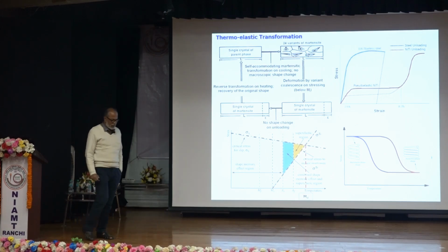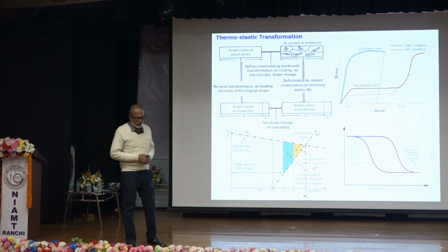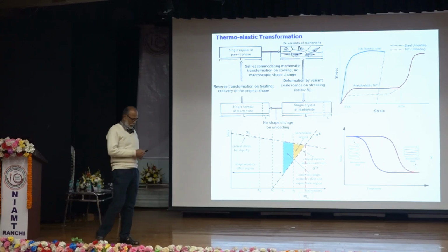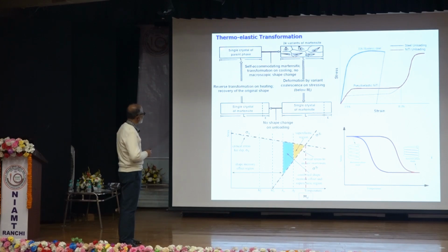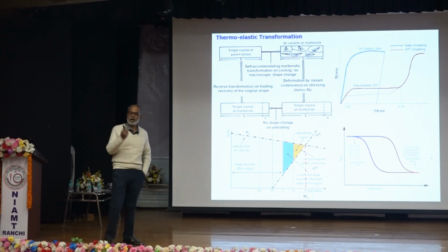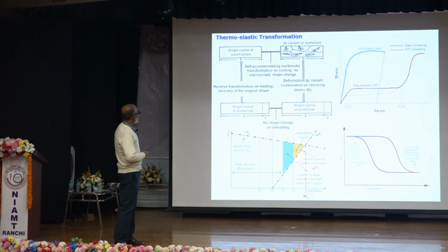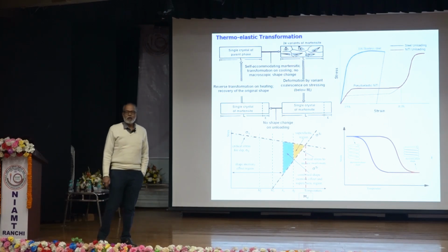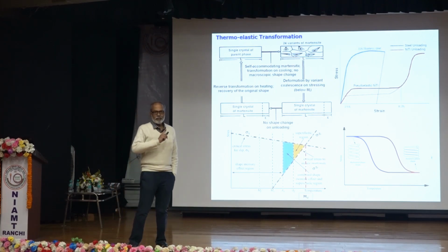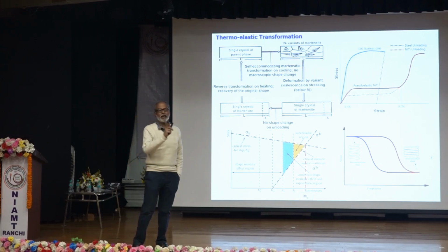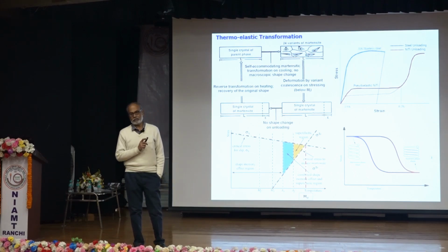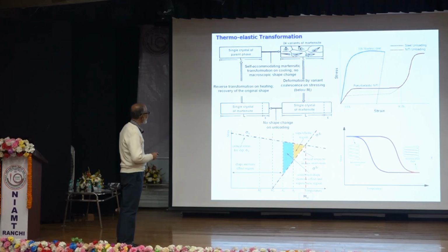Now, the martensites where invariant lattice strain is twin demonstrate certain unique behavior. For example, let us consider austenite and let us take a single crystal of austenite, say a grain of austenite. Let us consider an austenite grain, right? Cool it down, it will transform into martensite. But for compatibility between plane and line, there are 24 possible variants of martensite. Variant means 24 possible combinations of crystallographic plane and crystallographic line. 24 combinations possible, but all do not form. Those variants which are favorably oriented in the direction of strain are formed, right? So these variants are formed which are randomly distributed.